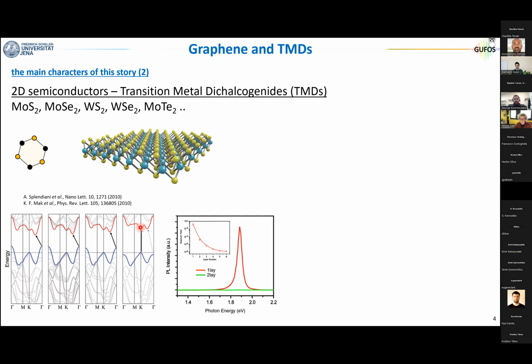There is one very peculiar feature of these transition metal dichalcogenides that we will use, and this is the fact, as it was demonstrated already back in 2010 by the groups of Tony Heinz and Feng Wang, that when you thin down these materials from the bulk form to the monolayer form, you have a transition from an indirect gap semiconductor. So this is the bulk case where you see the indirect gap is close to the gamma point. You have a transition to a direct gap semiconductor that this time occurs again at the K point.